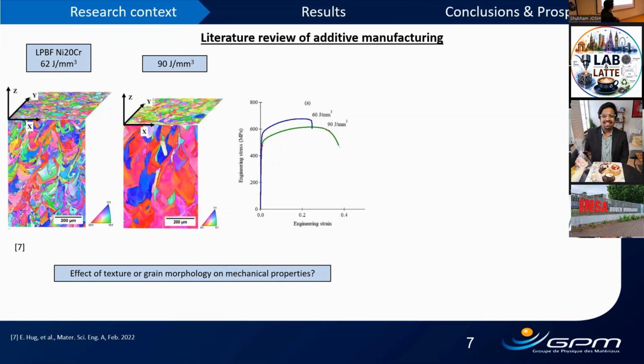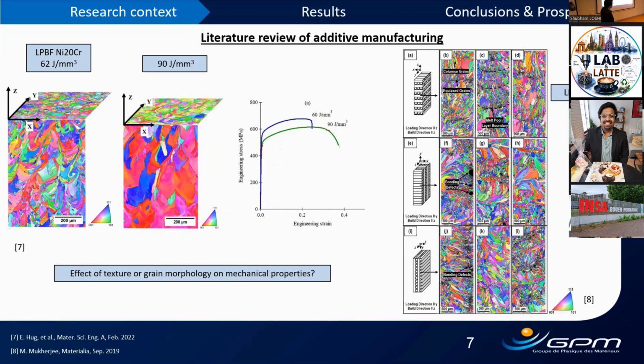And if we look at the engineering stress strain curves of the two differently processed alloys, we see there is a difference. So certainly there could be an impact of texture. Moreover, this is LPBF 316L and it's a bit complicated, so you could not look at all the images, but the takeaway from this second image is that the texture or grain morphology also depends on the building orientation, whether vertical or horizontal, and on how these building directions are oriented with respect to loading directions. So at the end of this slide, could we consider that it's the effect of texture or grain morphology on mechanical properties? Well, the question is still open.